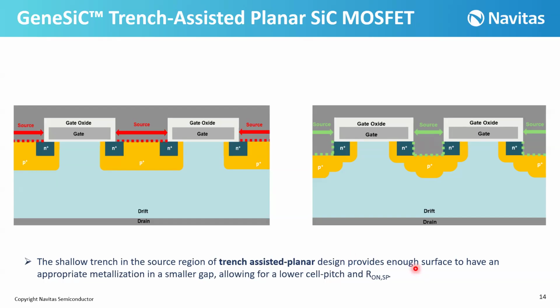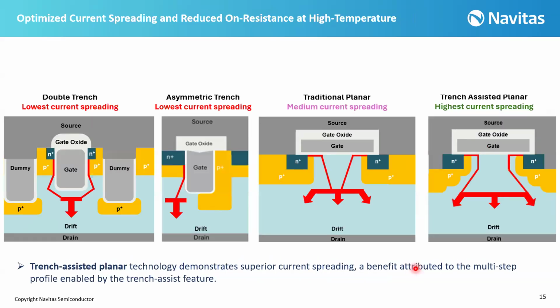All right. Another advantage is, thanks to having these multi-steps of P plus implantations, we are making a better current spreading compared to other planars, and obviously better than trenches. If you look at here, the current can easily spread over these steps and have a better current spreading compared to the traditional planar, as I mentioned. And this is one huge benefit, especially for high temperatures. And this is one reason that we have a lower RDS(on) at higher temperature compared to other designs.